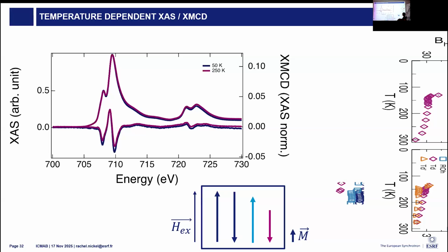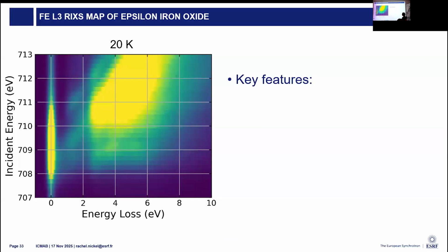Now, the XMCD in particular is a little bit confusing because we only expect 2 sites to contribute, and we don't see a notable change in the XMCD. So we went to a more powerful technique with RIXS. So this is an iron L3 RIXS map of epsilon iron oxide.